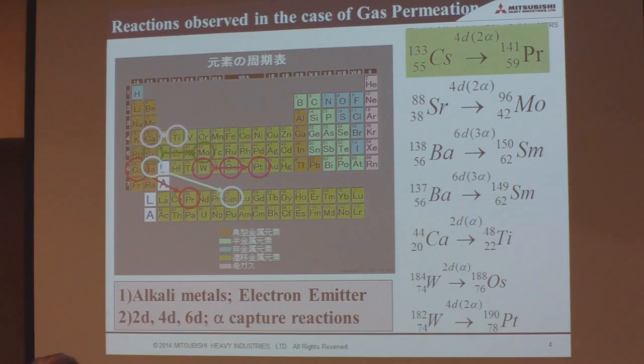If we summarize these experimental results, we can see some features of this permeation-induced transmutation. One is that alkali or alkaline earth metals, electron emitter elements, seem to be very easy to transmute by this method. And second, some rules exist between the target element and the product element. In this case, cesium plus 4D gets praseodymium. In the barium case, barium plus 6D gets samarium. So we can see some rule, 2D or 4D and 6D difference between target element and the product element. That's the summary of our experimental results.